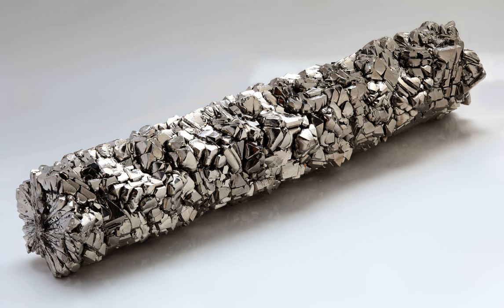Titanium has the inherent ability to osseointegrate, enabling use in dental implants that can last for over 30 years. This property is also useful for orthopedic implant applications. These benefit from titanium's lower modulus of elasticity (Young's modulus) to more closely match that of the bone that such devices are intended to repair. As a result, skeletal loads are more evenly shared between bone and implant, leading to a lower incidence of bone degradation due to stress shielding and periprosthetic bone fractures, which occur at the boundaries of orthopedic implants.